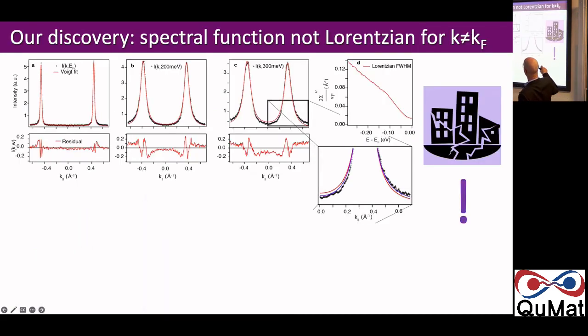So what they've noticed is, if you take, it doesn't matter which data because they all do it, the momentum distribution curve at the Fermi level, so at k equal to kF, this thing is a Lorentzian, right? We have extremely good signal to noise. The signal to noise on these data is about 300. So that means the signal at the peak is 300 times the up and down of the noise away from the peak. So this means we feel comfortable to discuss what the peak is doing away from its maximum.